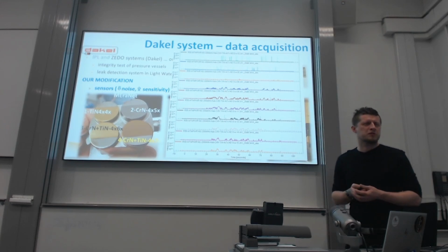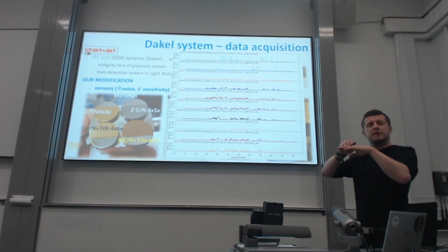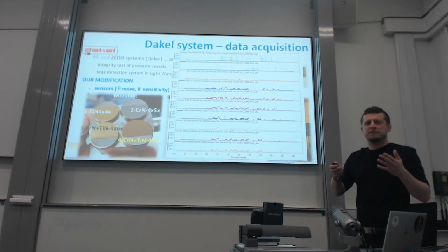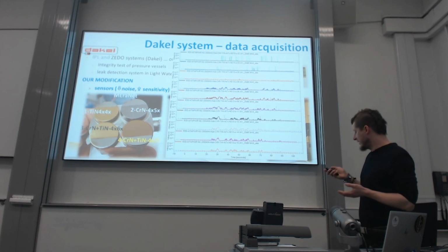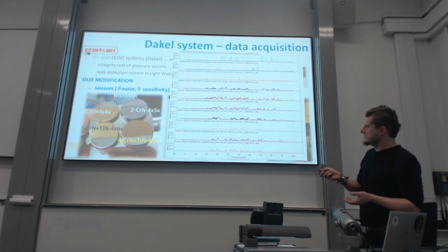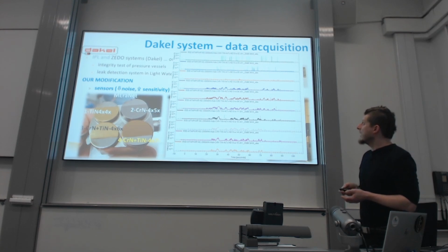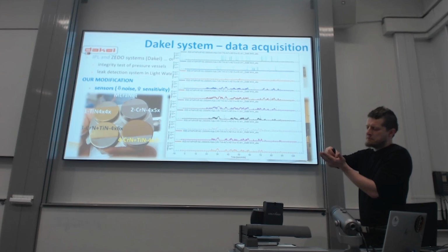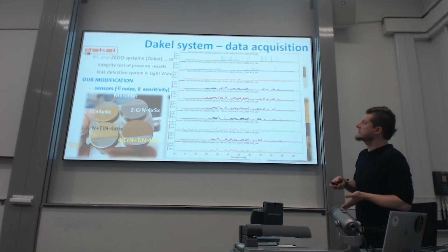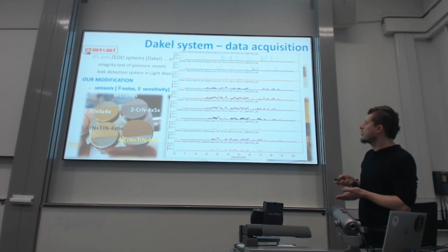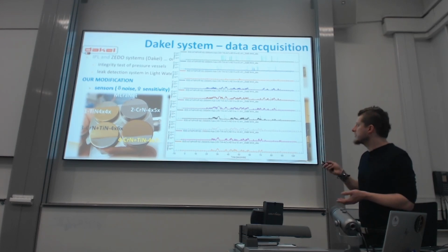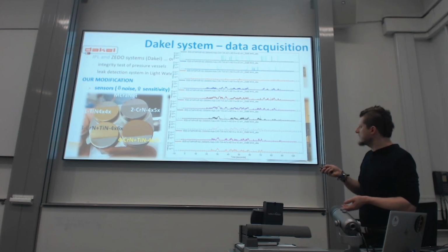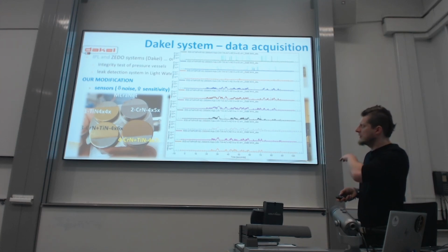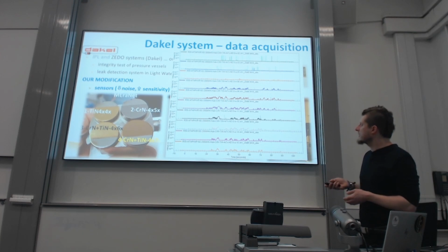As Ben told yesterday about multipass wear tests, so several tests at subcritical load, scratching and checking when something happens. It's like a sped-up wear test or something like that. So in the first scratch on these samples, we had a nice signal from the first plowing, because there is much more contact of the tip with the coating itself, and then there is less contact because it's already plastically deformed. And you see in the fourth loaded scratch, something happened. So we can see there is a deterioration of the coating, which again increases in every other step. So it's not that something happened here and nothing is happening here, but it's still on the same spot, a little more broken and cracking and something like that.